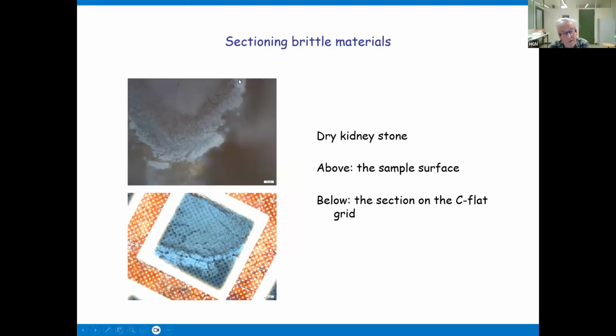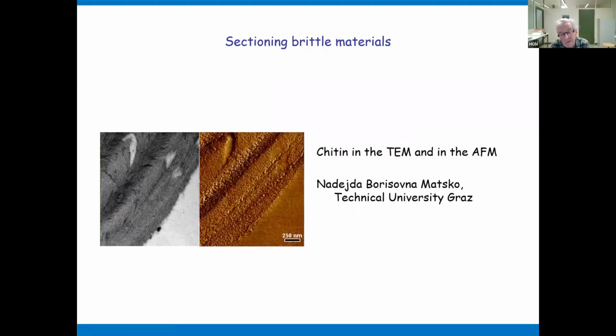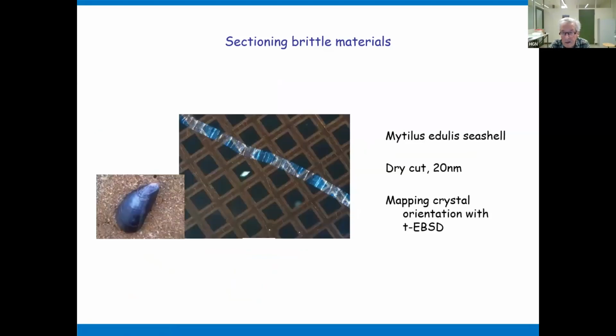You see the surface of the sample after the cutting. There was no embedding. This was simply clamped, cut, and you see the section, the same area here on the TEM grid. And again, if there were damage, you would see the lines here. Chitin is fairly brittle, it's not hard, no damage. The shells, the shell from mussels, it was done for transmission EBSD. You see the sections on the grid, and no damage at all from this sample.